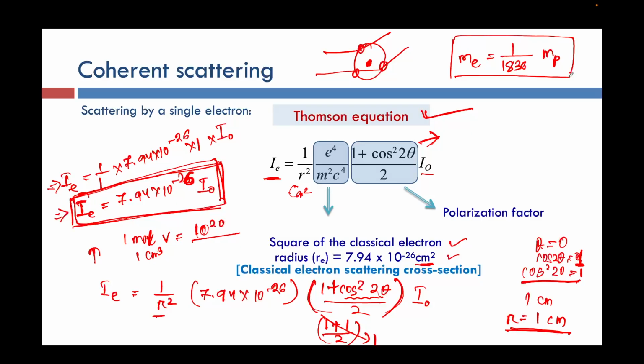So here the M is the mass of the scattering center, and it lies in the denominator. The mass of proton will be 1836 times the mass of electron. You have to not only put the mass of electron, but you also have to put 1836 square in the denominator. Then in that case the value will be extremely low, right?